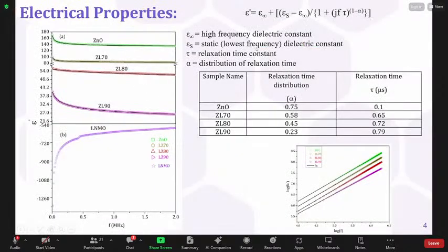To understand the electrical property, the dielectric constant was recorded with frequency from 20 Hz to 20 megahertz, which is fitted using the Cole-Cole relaxation model. The parameters from the relaxation model show the relaxation time distribution and relaxation time. As we saw in this graph, as in the individual graph, as we increase the frequency, the dielectric constant decreases, which shows that as the frequency increases, the dipoles do not have sufficient time to align with the electric field. That's why the dielectric constant is decreasing.